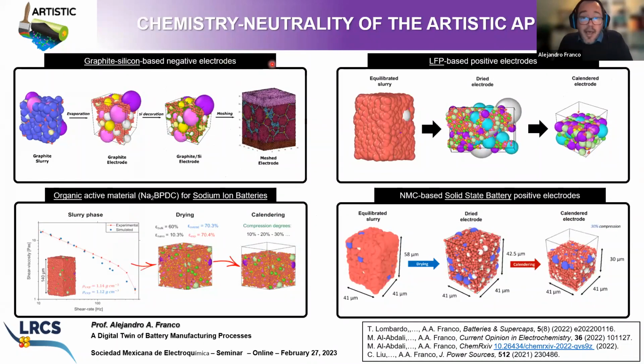So we have applied this physics-based modeling framework to different chemistries of active materials and different chemistries of cells. For instance, we have demonstrated the transferability of this approach for graphite-silicon-based negative electrodes, once again, for lithium-ion batteries, where we have simulated the entire manufacturing process, that means the slurry, the drying, the calendering, and we have even predicted the electrochemical-mechanical behavior of these silicon-graphite electrodes. You know, when silicon is being lithiated, it expands in volume by 300%, and then you have a lot of mechanical stress that is being generated inside the electrodes.